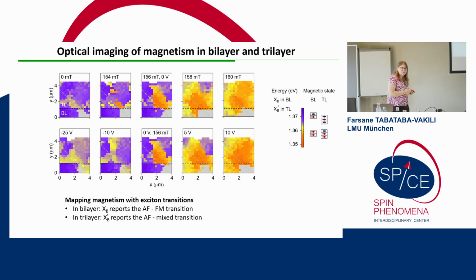Here, I'm showing another region on the sample where we have trilayer and adjacent bilayer, and the dotted line is the few layer graphene contact, which unfortunately goes right through the middle of this region. And in the trilayer, here we're tracking XB prime. As we increase our magnetic field, we observe this intermediate state that nucleates at the edge of this graphene contact, and it expands with increasing magnetic field. We can see that the intermediate state in the trilayer and the antiferromagnetic to ferromagnetic transition in the bilayer occur at the same magnetic field within resolution limit.